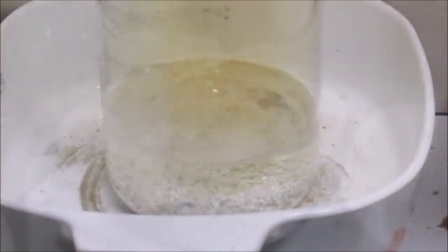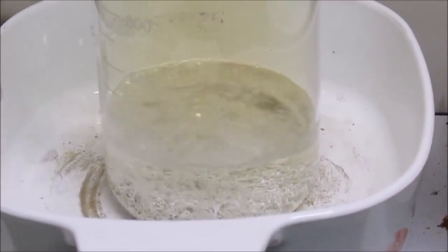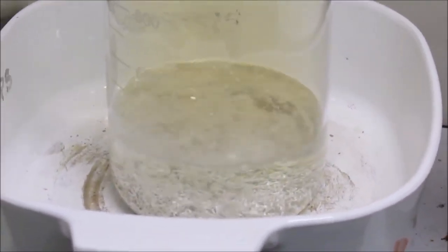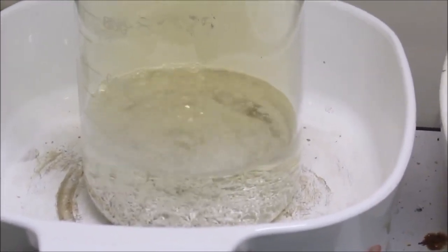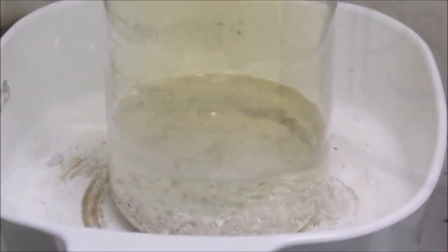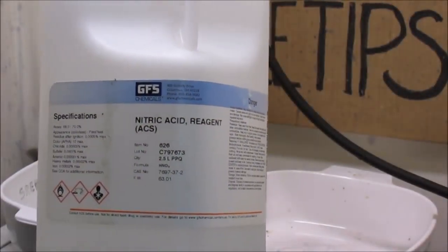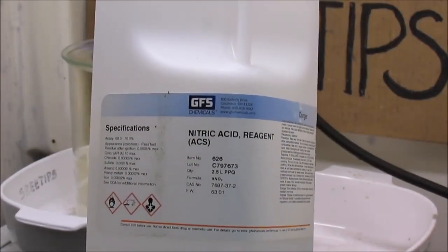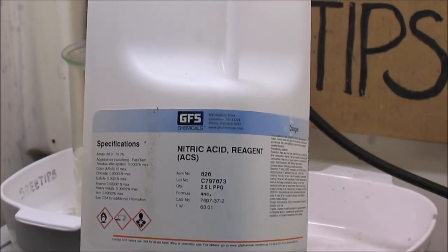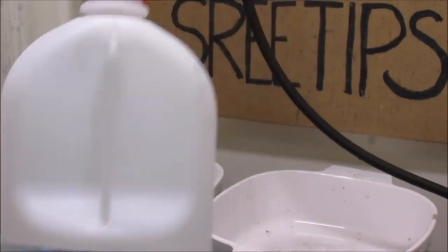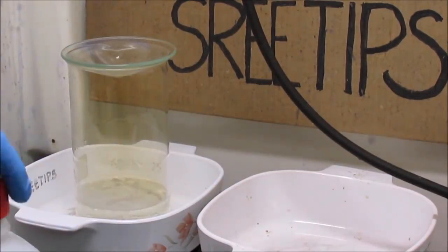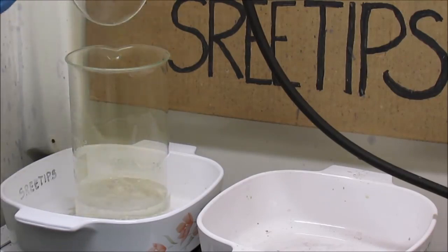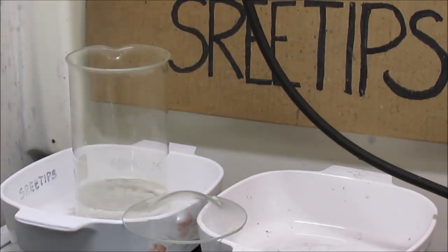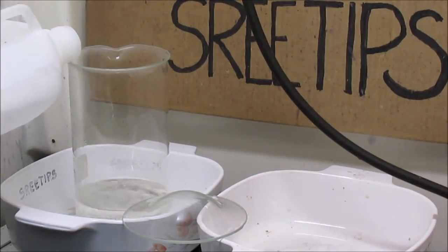The silver nitrate solution there has been boiling now for about an hour, and a little bit of the crystal has gone into solution. I'm going to add some more nitric acid now. I'm adding concentrated nitric acid here, about 68 to 70% concentration. Just going to pour it straight into the beaker there. This thing is hot, so I've got to do this real careful. Otherwise, it's going to want to boil over on me. Very slowly.